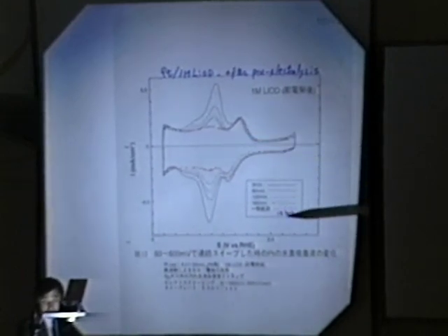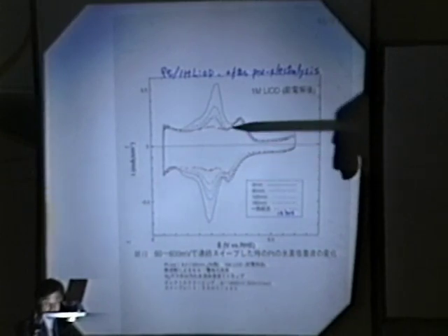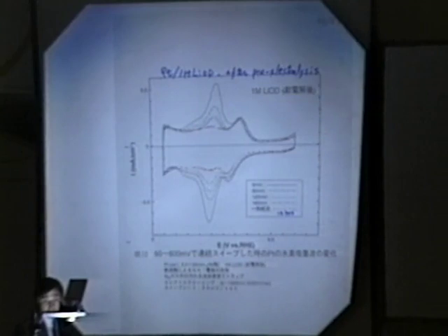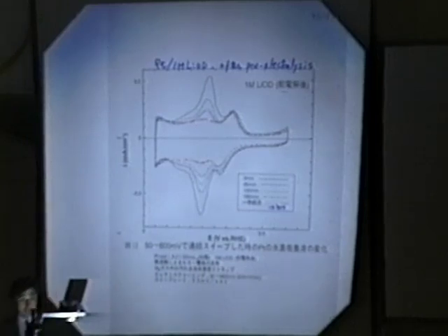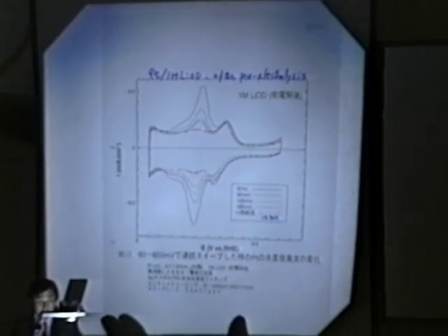if we leave the surface overnight, we still have a very clear current due to adsorption and desorption of hydrogen. Although this so-called weakly bound hydrogen region is greatly disturbed, still half of the surface remains clean. So this means we always have some contaminant on the surface or in the electrolyte. And this contaminant is not always bad, because it modifies the surface, and this may improve the cathode loading. But if we are interested in getting reproducible data, we should really purify the electrolyte. You may be lucky to pick up just the right contaminant, but we cannot rely on that sort of luck every time.